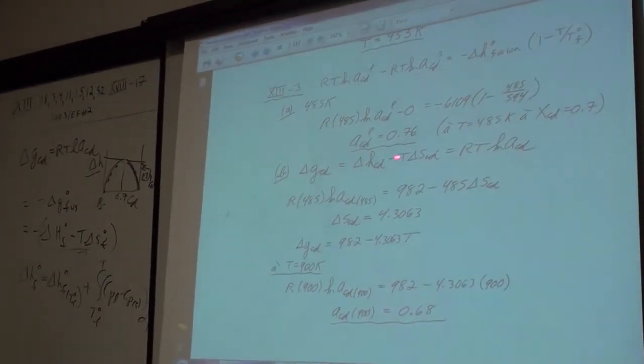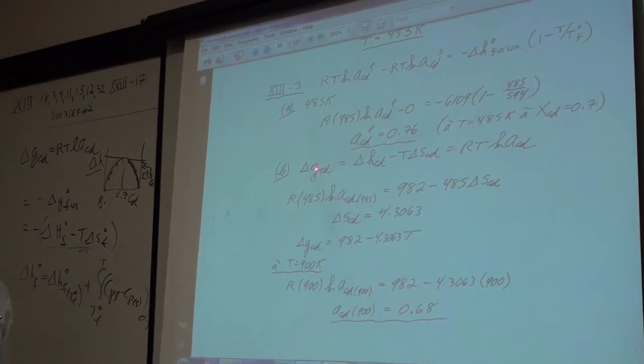Now you can also see, as I said last week, suppose that you decided, well, here I've got delta G of cadmium at one composition on the liquidus, then I need the heat of mixing. Well, I can do the same thing at different compositions along the liquidus, at 0.7, 0.8, 0.9, 0.6. Then I get delta G of cadmium equals delta H minus T delta S of cadmium at a number of composition-temperature coordinates along the liquidus. Now I have 2 or 3 points, so I could take this equation and smooth it out in order to get delta H and delta S from my non-isothermal calculations along the liquidus, but this would be completely wrong. There's no way you can separate delta H and delta S by a non-isothermal measurement.